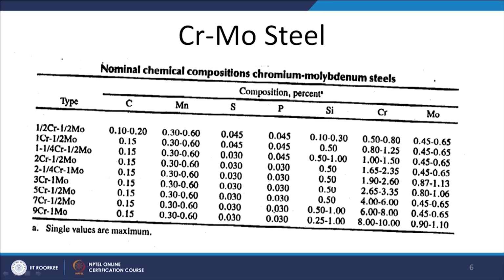Now we will see the most common grades of the chromium molybdenum steel, like the 0.5 chromium, 0.5 molybdenum. The first grade is like 0.5 chromium, 0.5 molybdenum, having chromium in the range of 0.5 to 0.8 and molybdenum 0.45 to 0.65. Likewise, there are different grades. One of the grades is 9 chromium, 1 molybdenum, having 0.15 carbon, and then we have chromium in the range of 8 to 10%, and the molybdenum is 0.9 to 1%. The single values show the maximum possible content of that particular element. So, in these grades the maximum content of carbon is say 0.15%.